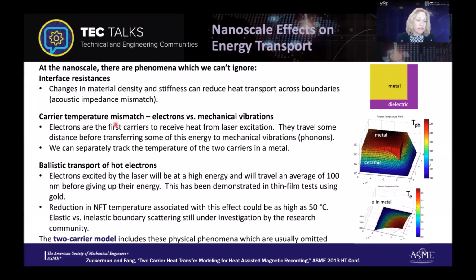We also have to be considering the carrier temperature mismatch. So when the disk is actually, all the electrons are what are going to be absorbing the energy from the laser, interacting with the laser. And when we're talking about a very short time scale here, it takes time for them to actually interact with the lattice and give their energy off to become heat in the lattice. And so the temperature of the electrons is actually going to be different for the time scale that we're talking about from the lattice vibrations or the phonons. And so we have to consider the different temperature between the electrons and the phonons or lattice vibrations in the device.